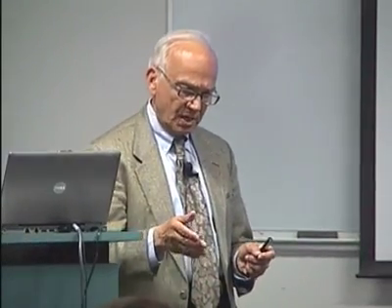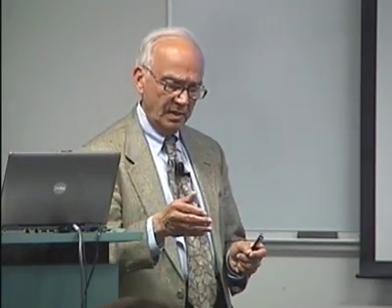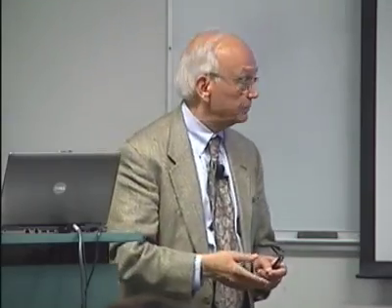phase separation occurs and is two-dimensional in nature in these indium gallium quaternary layers, occurs along the soft directions lying in the plane. There is no phase separation along the growth direction. And the wavelength that you see is on the order of, I will say, 8 nanometer, the structure that is produced.